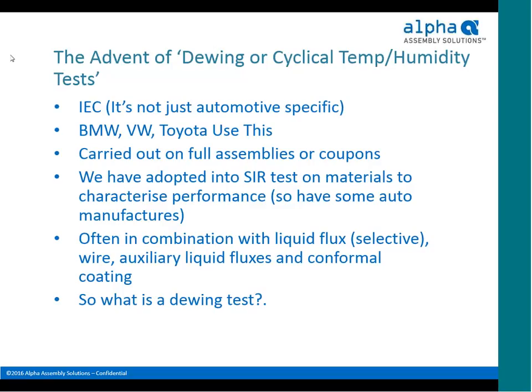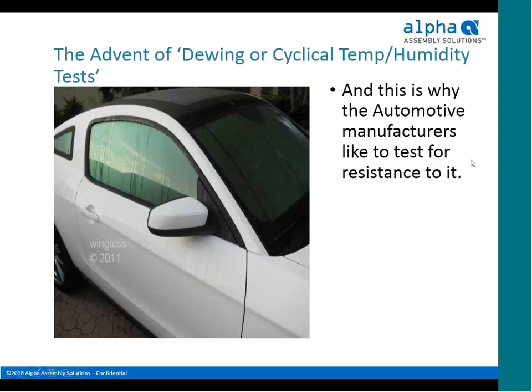This test is uniquely targeted for that exact combination because not only are you stressing the coupons with humidity and temperature, but you're also cycling that, so you're getting the effect of temperature cycles on the adhesion of conformal coatings to assemblies, and then testing the electrical performance of those material stack-ups together. So after all that, let's look at what a dewing test is.